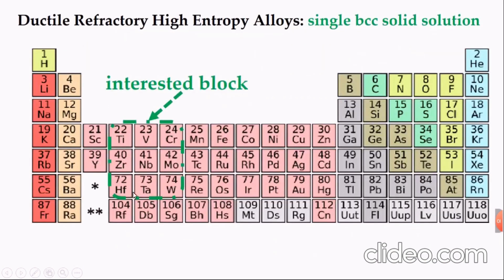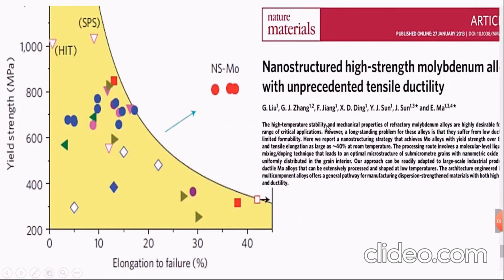Actually, some people give examples of ductile refractory high entropy alloys, and it's very strange when you hear ductile while we have refractory, which is very interesting actually. Some people suggested this block of elements to have a single BCC solid solution, and in a reported research, they could obtain molybdenum high entropy alloys with 40% ductility, which actually is a very high percentage of ductility for a refractory high entropy alloy.